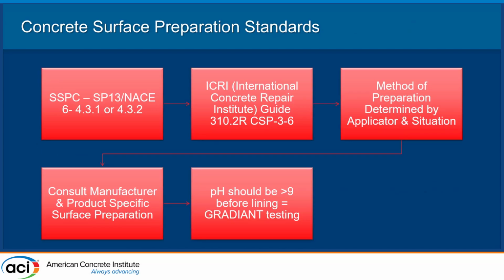So the surface prep standard that we recommend, if you're specifying a coating for concrete, and if you actually add in a surface prep standard, that gives the applicator, whoever's doing the surface prep, an actual standard to follow to get to a quantifiable result before the coating is applied. SSPC SP13 is the concrete surface prep standard that has been laid out, but we also include a concrete surface profile from the ICRI, the International Concrete Repair Institute, to give a visual comparator so you can actually give a visual confirmation that the surface prep has been reached according to the specification.